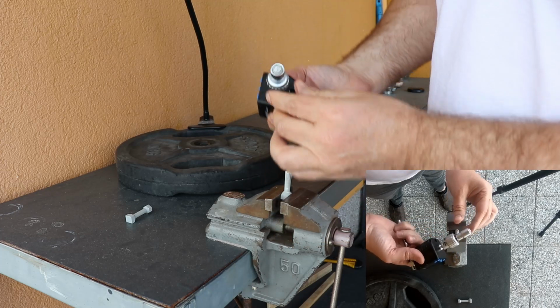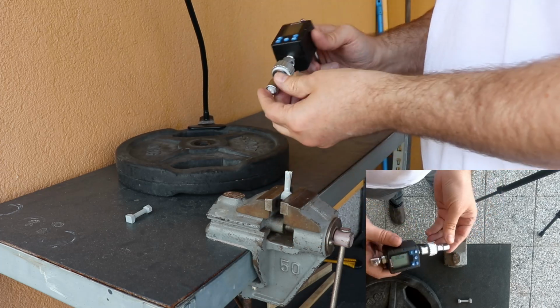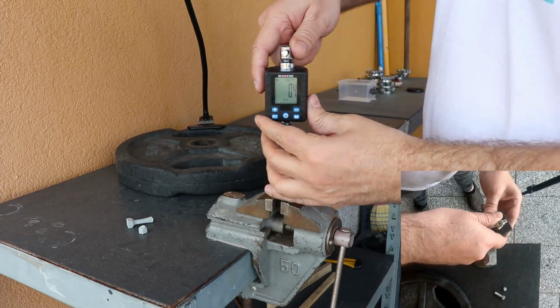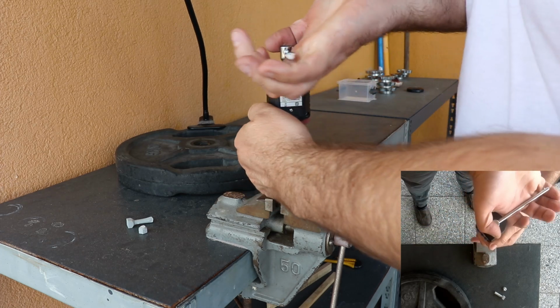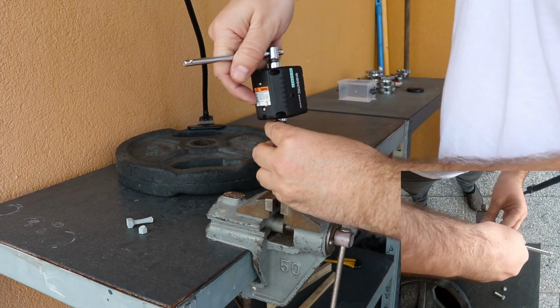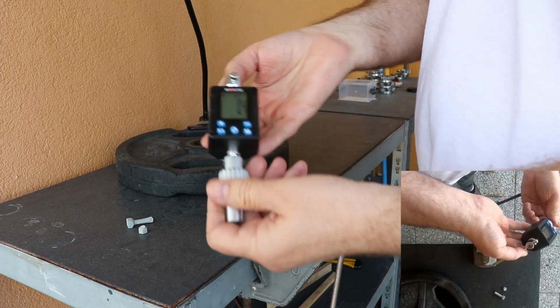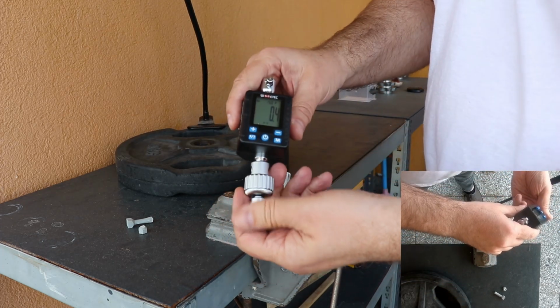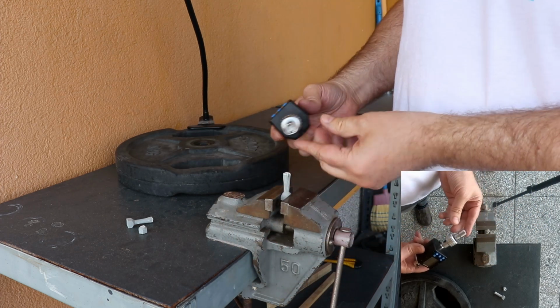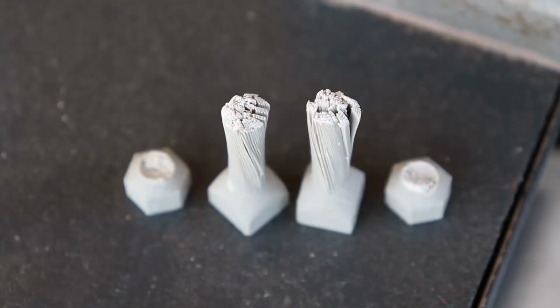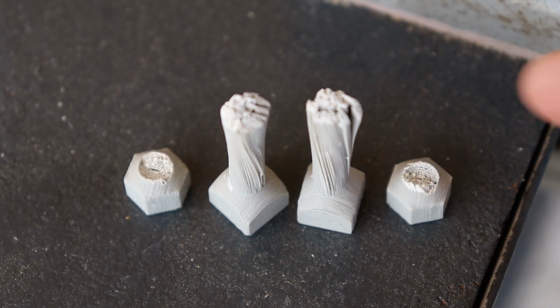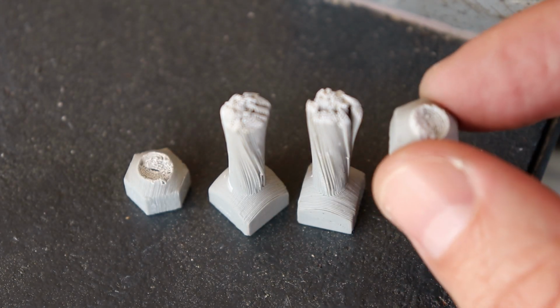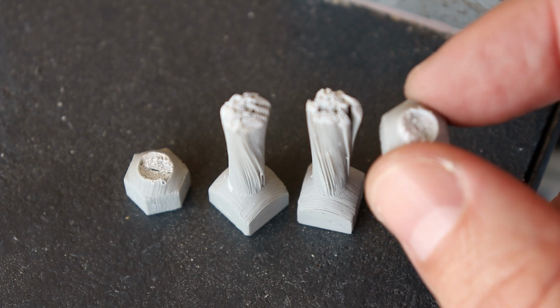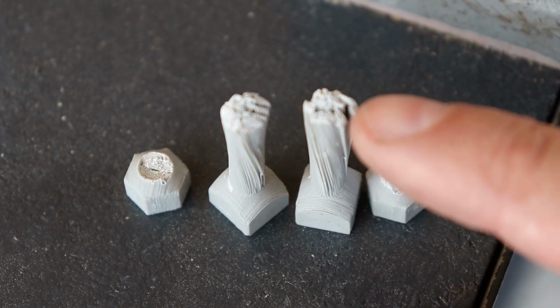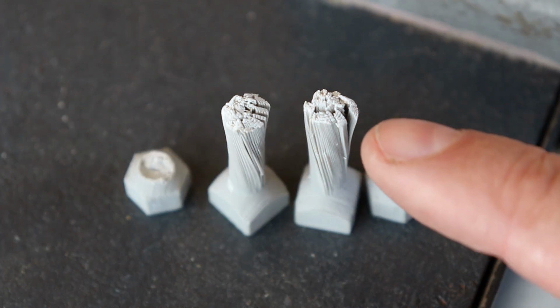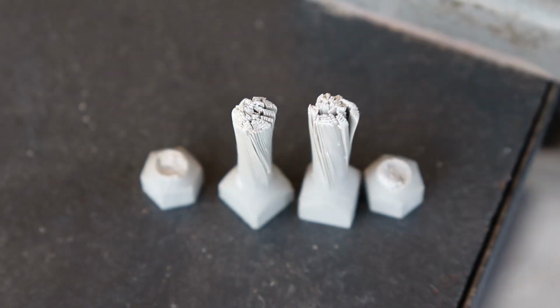Point 4. I think it's already broken, and again the peak is 0.4 Newton meters. And now, as I expected, because of that weaker layer adhesion, it performed very badly even in this torque test, and it can be definitely very visible that the layers separated from each other.